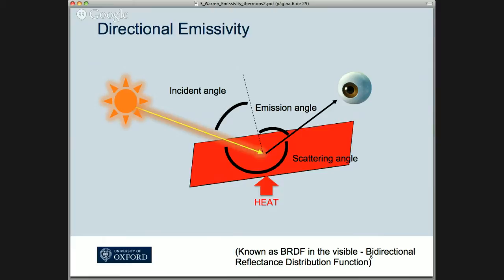Of course, one big difference between the infrared and the visible is that in the infrared, you don't actually need a light source. You can just heat the surface up from below and measure how it emits with varying emission angle. In that case, we just define our scattering angle from an arbitrary plane. For our experiment, we've started off just making measurements like this, heating the sample up from below without a light source, just to keep the experiment a bit simpler to start with.